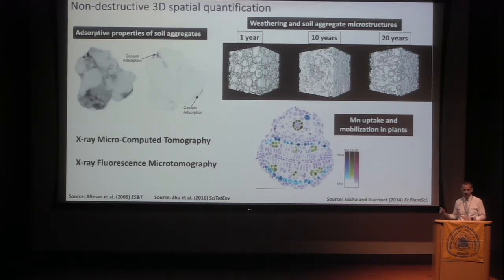In this case, this is a cross-section through a plant seed without having to physically cut through the seed. This is a virtual X-ray cross-section through the seed. This was a study focusing on manganese uptake through the plant from seed to sprout and then into a plant, trying to understand genetic and DNA controls over how manganese is removed and moves through the plant. This color map shows how manganese is specifically localized within parts of the seed in contrast to iron and zinc, which are in other places. This has the ability to open up trying to understand metal transport at, say, plant root mineral interfaces or micro mineral interfaces without having to do processing where we were potentially losing or damaging information along the way.